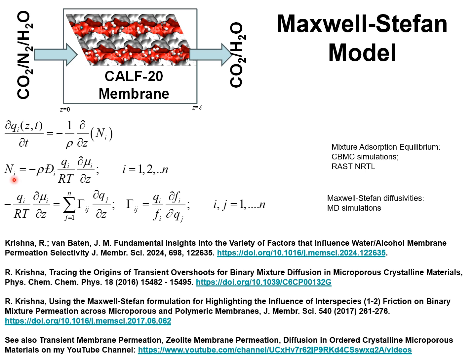This permeation flux is described by the Maxwell-Stefan diffusion formulation as being proportional to the gradient of the chemical potential, and the component diffusivity is D sub i.